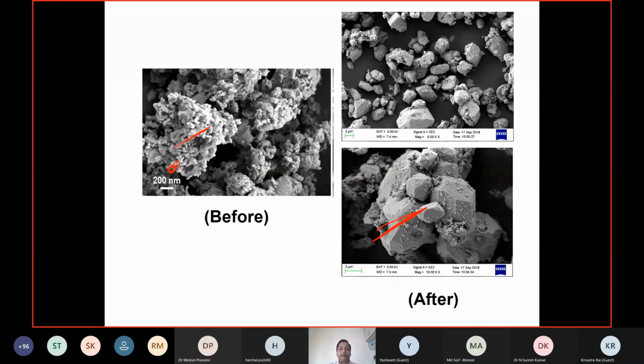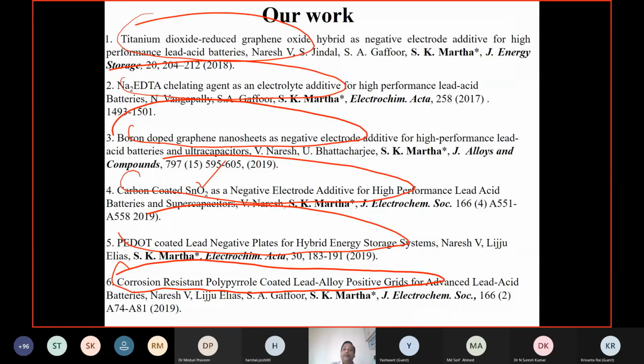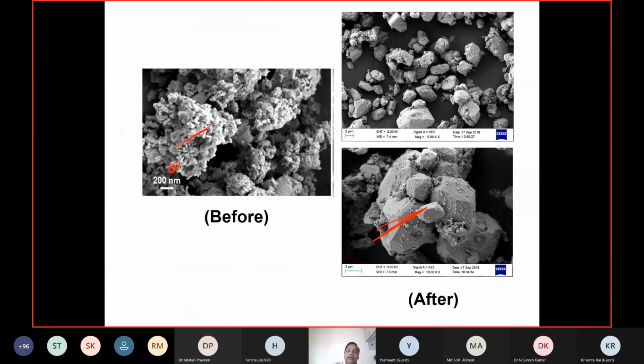Okay, it is just in 500 cycles. This is a scanning electron micrograph. That means you have a big growth of the particle. So how to improve the conductivity of the paste? Most importantly, to improve the conductivity of the paste so that bigger lead sulfates are not produced. Maybe instead of 500 cycles, it goes to 1000 cycles. Can I improve from 1000 cycles to 2000 cycles with different additives? This is a small insight.